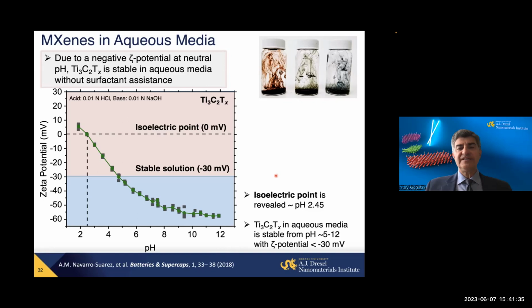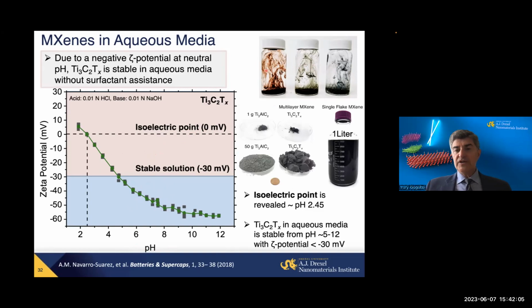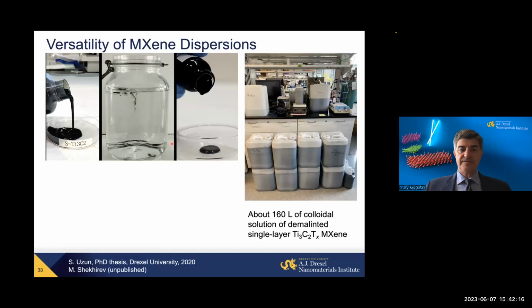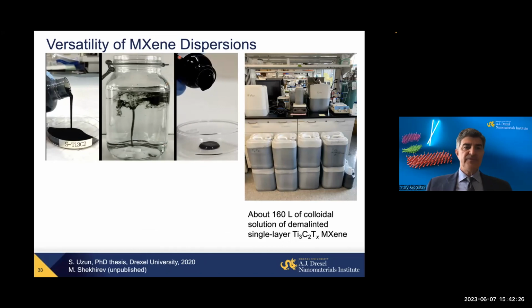And what is important, MXenes have a high negative zeta potential, below minus 30 millivolts at close to neutral pH. What it means is that you can disperse them in water again, unlike graphene, but very similar to graphene oxide, without any surfactant, any additive. And you see different MXenes also give you different colors because they have different electronic structures. So we take ceramic powder, put it in solution or emulsion salt, etch it, disperse in water, and we get a colloidal solution of 2D flakes. And as you can see from this movie, and I hope it will play. Doesn't want to, but now it plays. You can see MXene disperses in water.